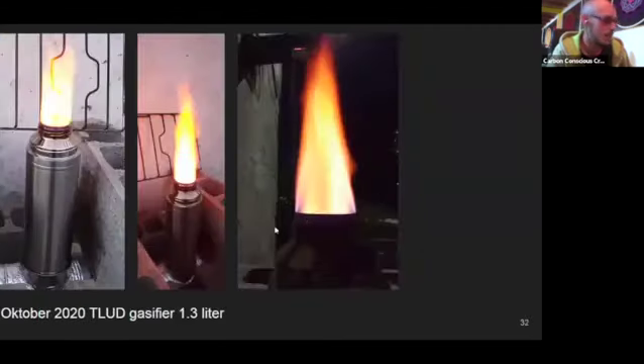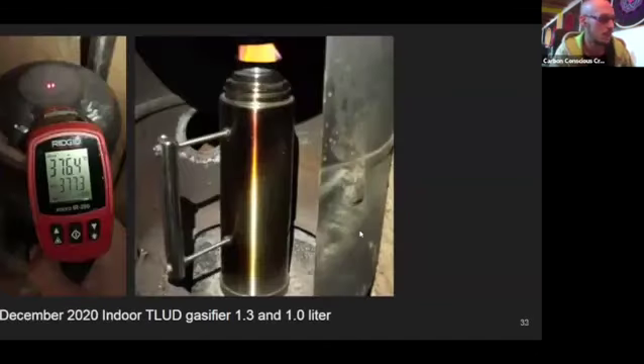And then at a certain point, I realized that the small TLUD gasifier I had actually burned the cleanest. So I went back to small, and this time with a 1.3-liter thermos flask. And then I turned that also into an indoor stove. So this is in the same location where I had the large masonry system, the first indoor system, which I started demolishing, and I put a small metal version with this 1.3-liter TLUD gasifier there.